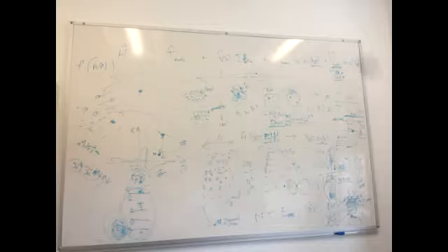GGA lattice constant will be larger than experimental. So you need to know these tiny things and just to know, okay, I've calculated this value, compared it to experiment, it's 2% larger. Is it okay, or am I doing something wrong? That's okay. But if you got a lattice constant which is 2% smaller than experimental, then you are doing something wrong, because GGA should be higher.